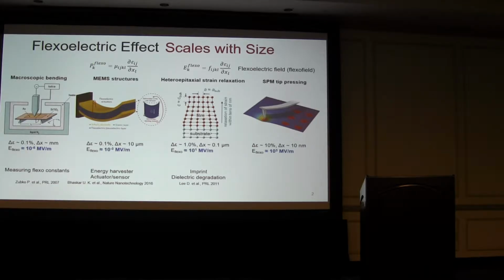The most significant case where flexoelectricity plays a role could be the pressing of a scanning probe tip onto the film sample. It has been shown that this high flexo field could create 180-degree polarization switching, and it also influences the transport locally in the systems. So my interest is focused on this scheme, where the flexoelectric effect plays the most significant role.